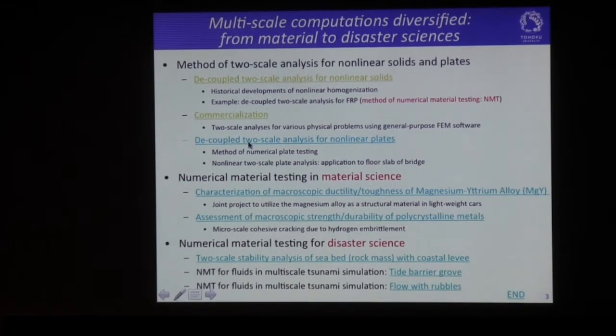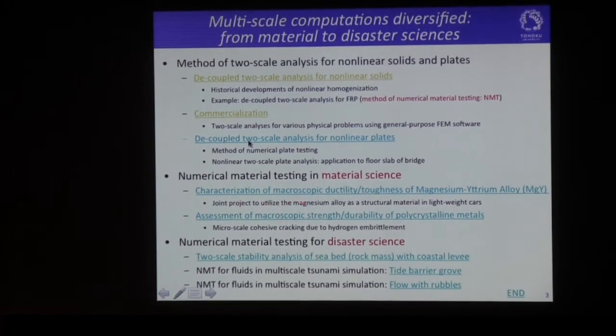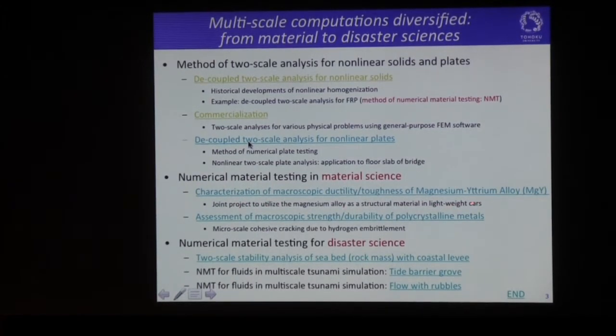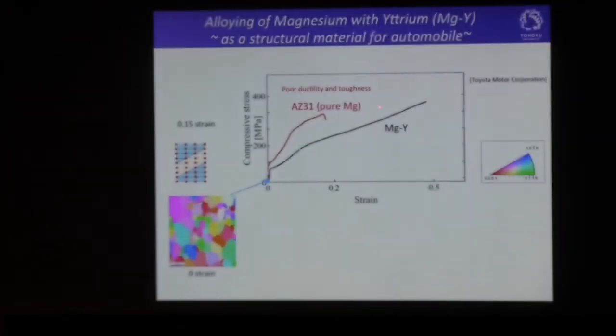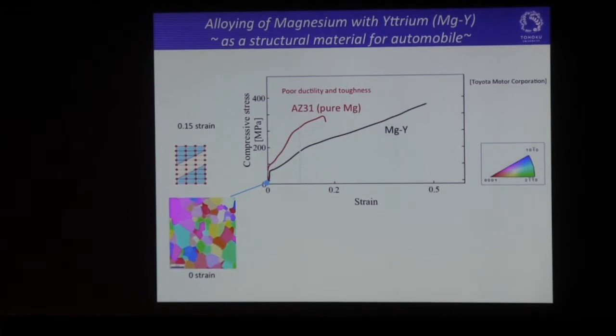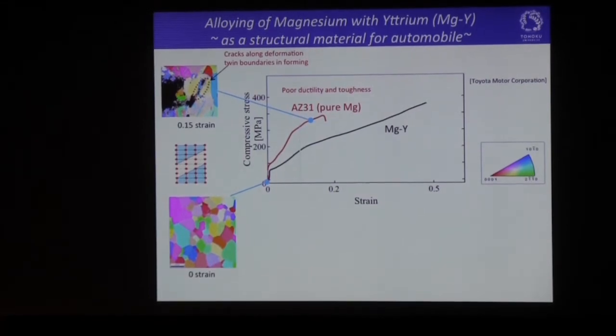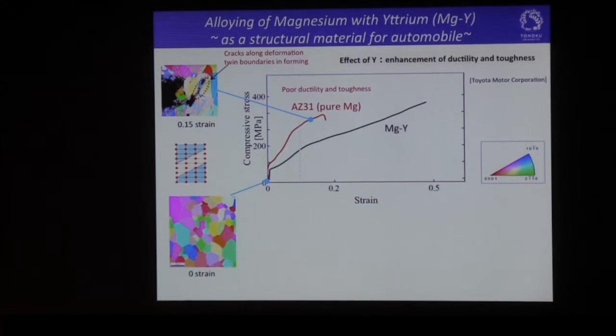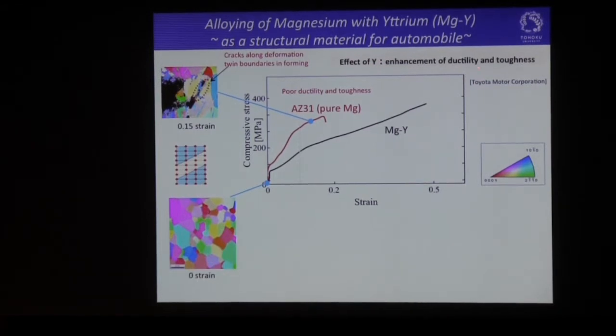So let us move on to the next topic, that is the numerical material testing in material science. We have two topics today. One of them is the characterization of the macroscopic ductility and the toughness of magnesium yttrium alloy. This is the joint research to utilize magnesium alloy as a structural material in lightweight cars. Okay. Here, this is a typical stress strain curve of pure magnesium, and also the curve for the magnesium alloy. This pure magnesium shows poor ductility and toughness because this material suffers from cracks in the microstructure like this. On the other hand, this magnesium alloy shows good ductility and toughness. It is clear the effect of yttrium is the enhancement of ductility and toughness.